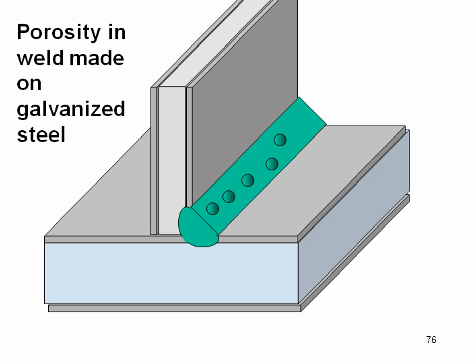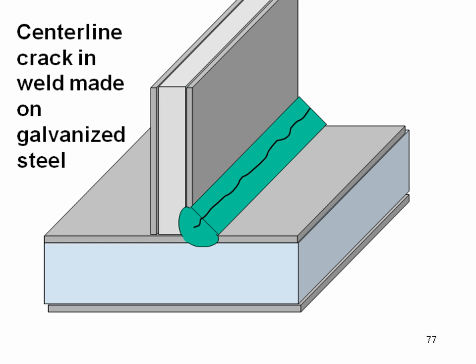The other problem is that you may introduce zinc into the liquid weld metal. And if you do that, the zinc, with a different melting temperature, may segregate during solidification and cooling. It goes to grain boundaries, or it may go to the center line of the weld, and we could get a crack. Now, cracks are the worst thing that we have when we try to make a weld. And so we need to preclude the cracking tendency in particular.